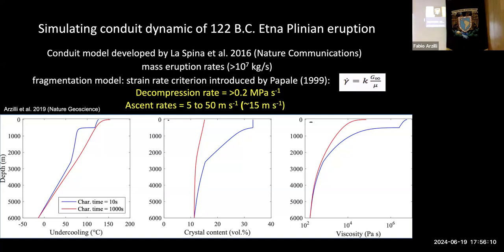Here we start from 6 kilometers, simulating a magma chamber at 6 kilometers, and then investigating conduit dynamics. Here we tracked the evolution of undercooling during ascent. Here you see the crystal content during ascent, considering the fast and slow crystallization. As you can see, when the system approaches equilibrium really quickly, the crystal content, plagioclase and pyroxene, can increase quite fast in the last 3 kilometers, up to this point. This discontinuity is related to magma viscosity. It means that the model is showing a transition in rheological behavior. This is the fragmentation level, and this was induced by a really fast magma viscosity increase, because crystallization is highly promoted in the last 3 kilometers, up to 10 to the 6 Pascal second.